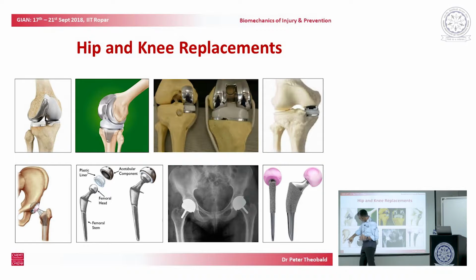But there is risk of having movement again because you've got two interfaces, or one interface between two materials, so that you could generate wear particles between the ceramic and the metal. If you were to generate wear particles, then those wear particles would be very hard because they're either from ceramic or metal, and so the risk of those wear particles creating further damage and further wear is greater than where you have wear particles from here. These wear particles from the polyethylene only will be relatively soft. If you have wear particles from a ceramic and metal interface, then you're going to have hard particles that very quickly accelerate further wear.